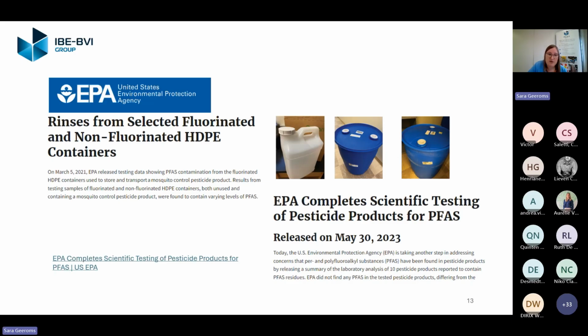Here, the material is treated on the inside with fluorine gas, and PFAS are actually formed as a side product. But thus, since there is contact with the pesticides on the inside, they are being contaminated, and thus the pesticides with the PFAS contamination are spread over the fields.